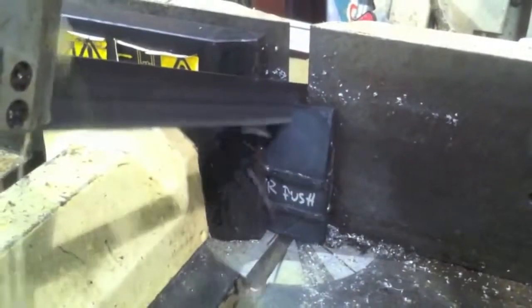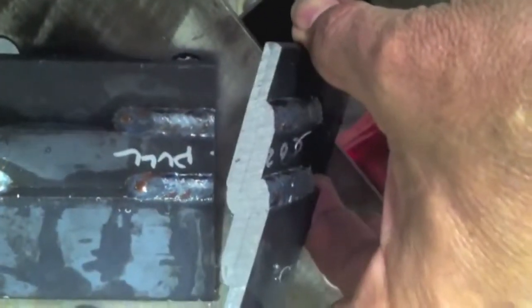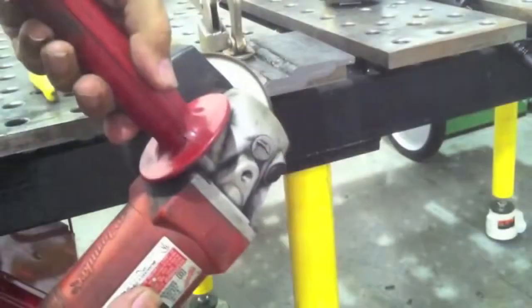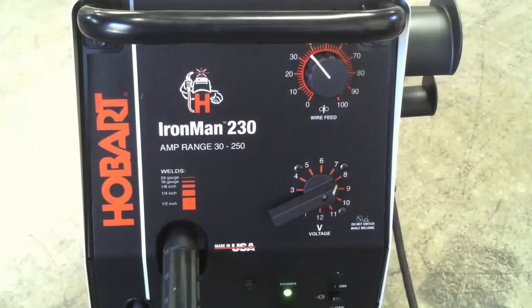Also had a chance to weld with some straight CO2 on 1/4-inch hot rolled and compare it to 75-25 argon CO2. Did some slicing and dicing to check for penetration on the straight CO2 versus the 75-25. A little polishing, a little etching, check for penetration, and saw that that machine penetrated very well with the right settings.